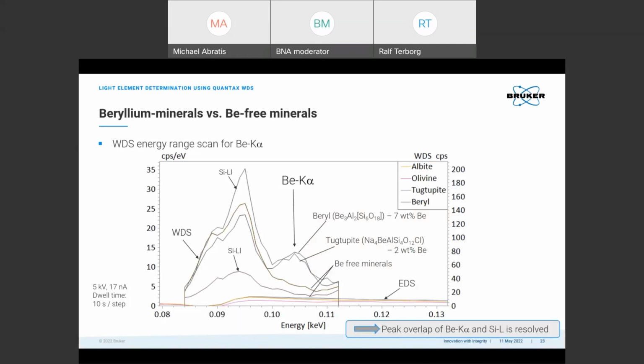All 4 minerals are silicates, so they all show a peak for silicon L. And the actual challenge for X-ray analysis is to resolve beryllium K from silicon L as a prerequisite for beryllium determination. This resolution cannot be done by EDS, but only by WDS.